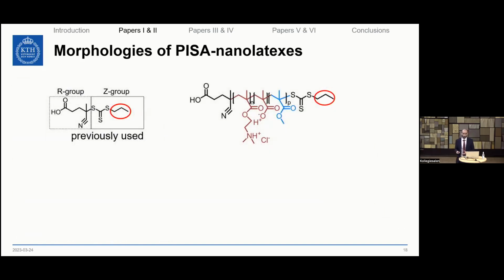Previously in our group, we have prepared monomodal and monodispersed nanolatexes that are comprised of a protonated PDMAEMA shell and a hydrophobic PMMA core, where the Z group of the RAFT agent that we used was an aliphatic chain.